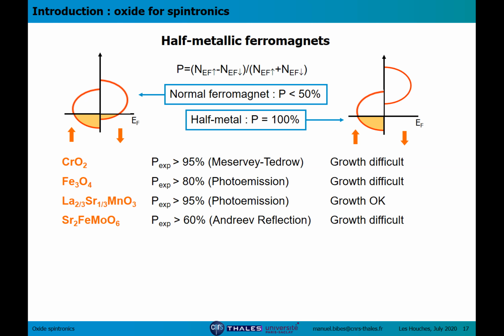LSMO is a perovskite. It's relatively easy to grow by PLD or MBE or sputtering. And early on, there were some results showing large spin polarization using spin-dependent photoemission, around 90–95%.